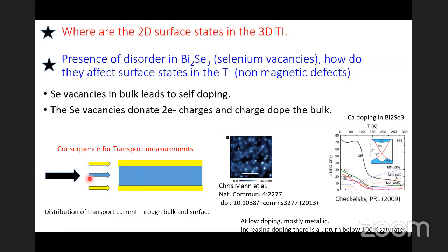And then if you send in current, the current not only goes through the highly conducting surface states, which are shown in yellow, but also goes through the bulk of the material, because now the bulk is no longer insulating. Doping by the selenium vacancy intrinsically dopes the system, and you get conductivity even in the bulk. And this was shown through experiments: without Ca doping, if you have selenium vacancies, the conductivity turns out to be metallic. But if you kill these by Ca doping, you can remove these dopant vacancies, and then you can show that you again make the bulk insulating.